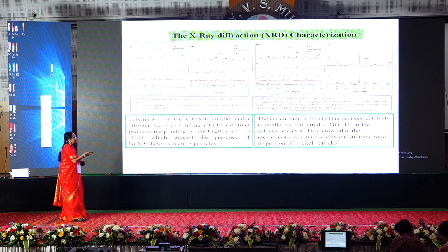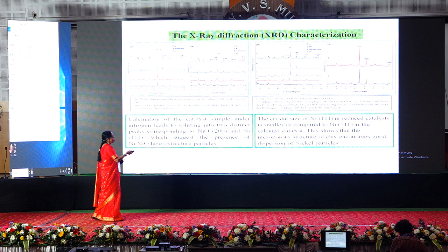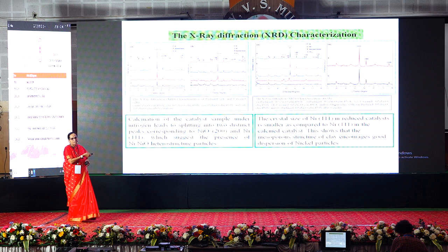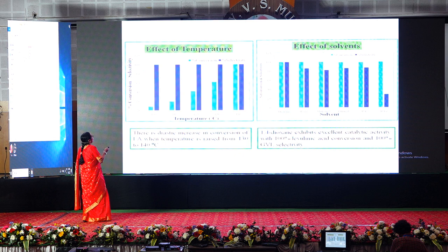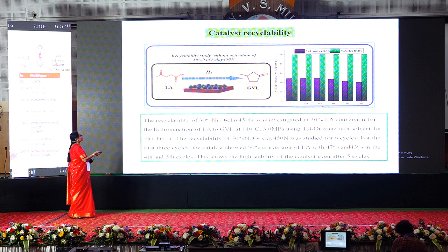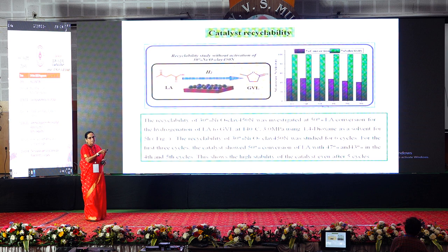And you can see this shows the mesoporous structure of the clay, which encourages good dispersion of the nickel catalyst particles, and which is very good. And also we showed the effect of temperature and solvents, and then we did the reaction. And also we did the catalyst reusability. Some of the processes we have patented, and we are going to commercialize some of them soon.